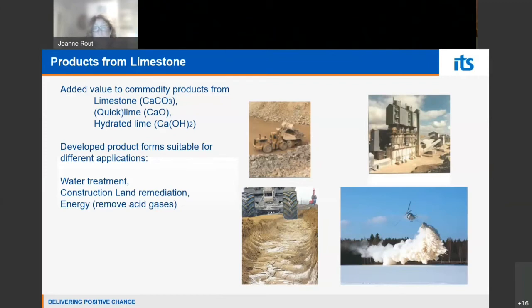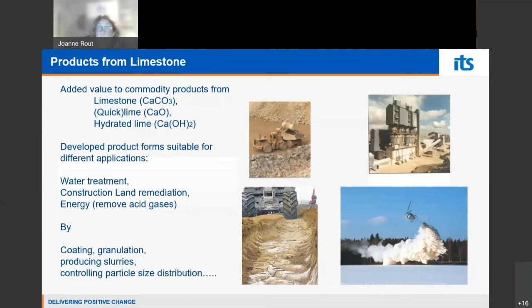Another big application of lime is when you burn coal, it contains acid gases, HCl, mainly sulfur dioxide, those sorts of SOx, NOx. So you can spray lime, or components of lime, as the combustion gases are formed, to remove those acid gases. Quite often you would form something like calcium sulfate, which is gypsum, which can also be used in construction. So we were looking at coating the product, granulating it, producing slurries, controlling particle size distribution to get the reactivity and the effects that the customer required.